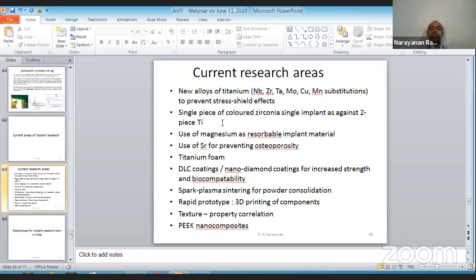The other area of research is the use of zirconium oxide, ZrO2, as a single-piece dental screw implant, as against the two pieces of titanium. This is one such area. And magnesium has been used as a resorbable implant material. Unfortunately, magnesium dissolves even before the desired lifetime. So if people can come up with certain additions, magnesium with calcium or magnesium with zinc, which can improve its resorbing nature, it will do a very good service because magnesium is very lightweight. So compared to stainless steel or titanium, magnesium is much better in this.